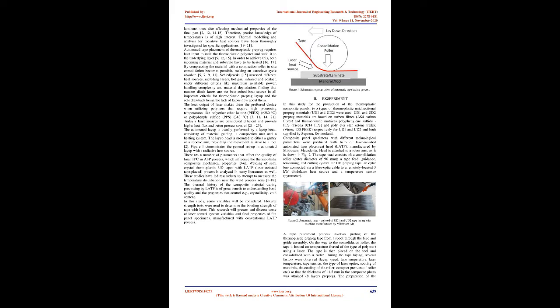5, 7, 9, 11. Schledjewski [15] assessed different heat sources, including lasers, hot gas, infrared, and contact, under different criteria like maximum available power, handling complexity, and material degradation, finding that modern diode lasers are the best suited heat source in all important criteria for thermoplastic prepreg layup, the sole drawback being the lack of know-how about them.